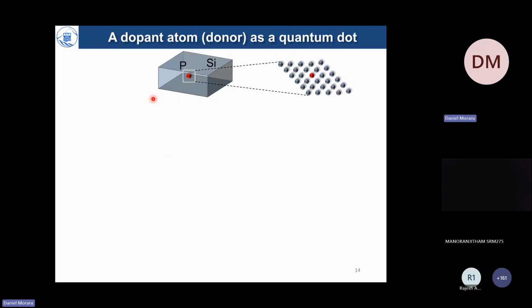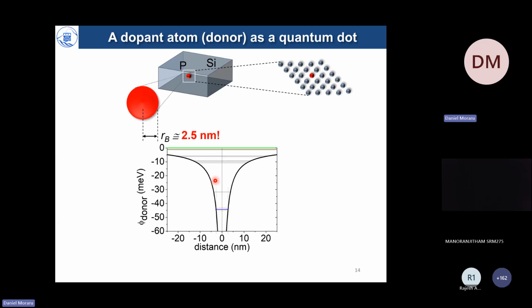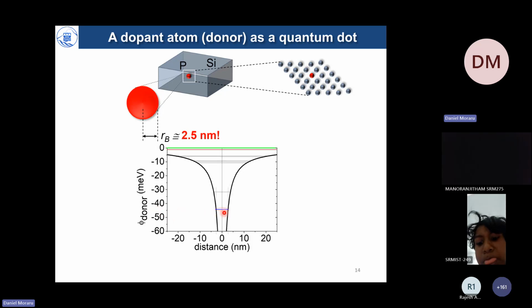A dopant atom, many of you may know, is a charge carrier provider. Let's say the phosphorus donor in silicon, substitutionally, modulates the potential around its nucleus on a radius called the Bohr radius, of about 2.5 nanometers. Once ionized, P+, this phosphorus introduces a Coulombic potential well around its nucleus, and it has a ground state around 45 millielectron volts below the conduction band edge, which is this green line.